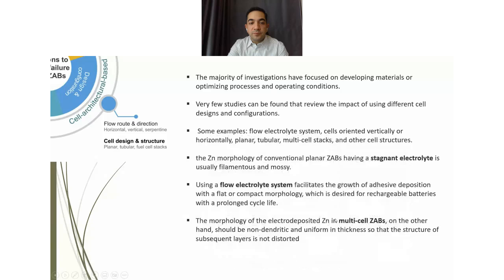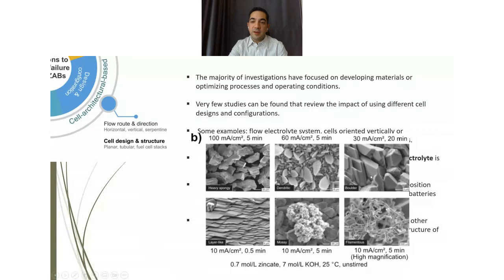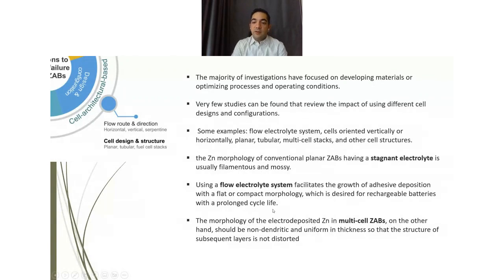And for the flow electrolyte system, it facilitates the growth of adhesive deposit with flat or compact morphology. So when we're using flow system, our morphology will more likely be like a boulder shape or layer shape, but it is very compact and dense. And when we're using multi-cell zinc batteries, the smooth morphology is very preferable, and it should not be dendritic. So as you can see, any cell configuration we use will require some specific ideal morphology for our operations.